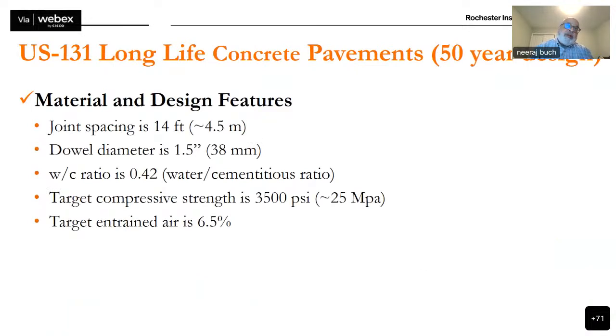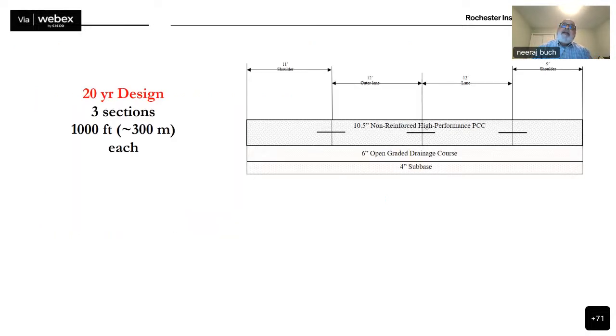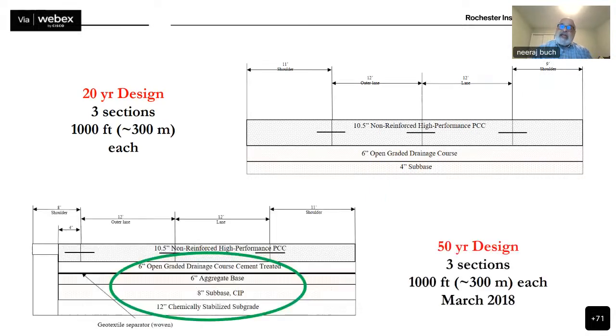For the US 131, which was a 50-year design, again, very similar structural characteristics. Again, a jointed plain concrete pavement. 4.5 meters contraction joint spacing, dowel diameter of 38 millimeters, water cementitious ratio of 0.42, target cylinder compressive strength of 3,500 psi or 25 megapascals, and a target entrained air of 6.5%. Again, here, a 20-year design was constructed as well as a 50-year design was constructed.